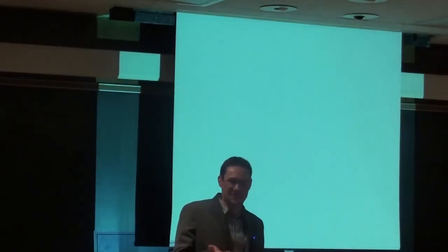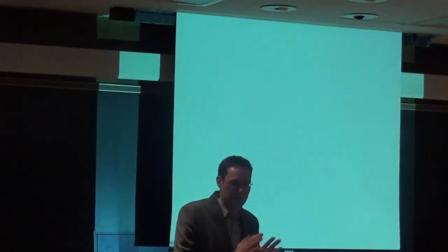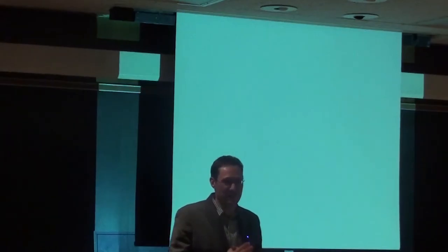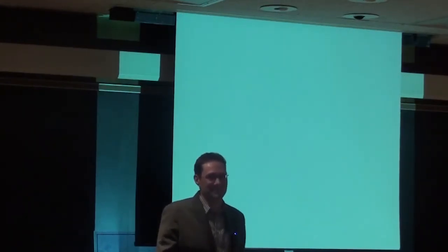Yeah. The roughness is, actually, we did this process several times. What happens is basically that you're etching, then you're reoxidizing. That takes actually longer than 6 hours in order to get full surface reconstruction. And then you do it again. And it turns out that this is rather reproducible. The question is, would you really expect that you have the same roughness after the first and after the second etching? I would not expect this, because usually the etching is quite violent. So we measured this two or three times.